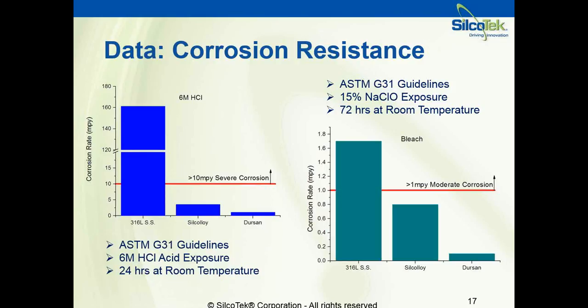So just to show you briefly some of the corrosion-resistant properties of the coatings, in this one we've selected Silcoloy and Dursan to compare to 316L, and we're doing basic immersion testing that we performed here at SilcoTek under the ASTM G31 guidelines. 24 hours at room temperature. You'll see on the left 6 molar HCl.